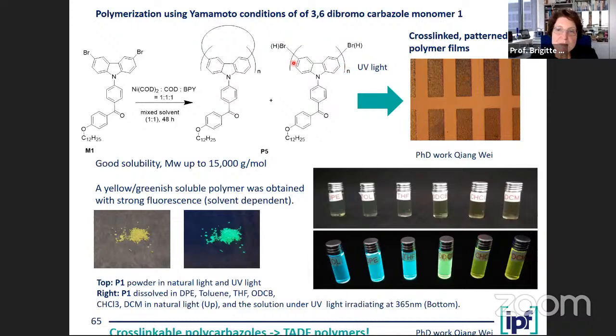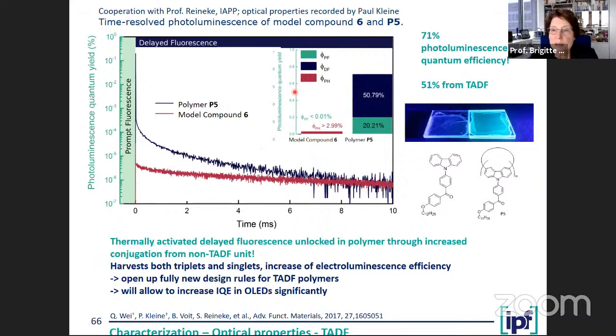We made this polymer. We actually thought it's a nice fluorescent material which we can use, or we can cross-link. But when we looked at it a bit closer and also had our partners involved, they noticed that this material has a very specific fluorescent activity, a so-called thermally activated delayed fluorescence. And this one harvests both the triplets and the singlets from the material. So you get a much higher output of fluorescence than you can get with other materials.